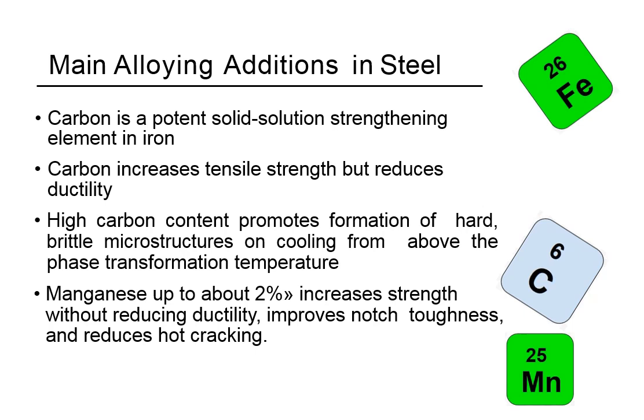So that's why we throw in manganese sometimes to increase strength without reducing ductility. It improves notch toughness and reduces hot cracking. So a lot of times you'll throw manganese in a steel like it says here. It increases the strength, but you're not losing the ductility. So it's not a really hard, high tensile strength piece of glass, so to say. The manganese helps keep the ductility in a range that's something you can work with. It makes it a useful tool.